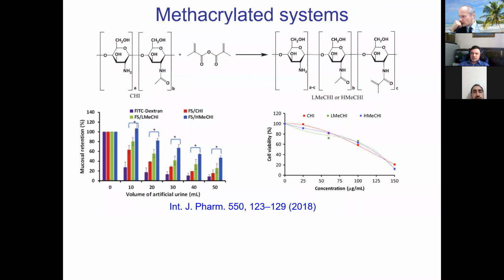We also have developed a number of methacrylated systems, such as methacrylated chitosan, by reacting chitosan with methacrylic anhydride. We looked at a model of the urinary bladder in this case, and demonstrated that this methacrylated chitosan is much more adhesive compared to conventional chitosan. This time, in terms of toxicology, we used a conventional cell culture assay, the MTT assay, and we demonstrated that the methacrylated version of chitosan is not toxic, and its toxicology profile is similar to unmodified chitosan.